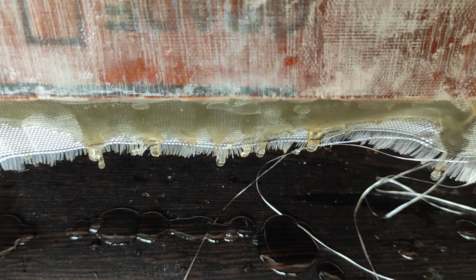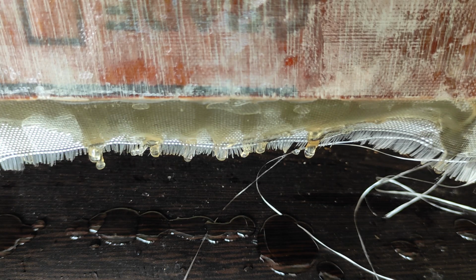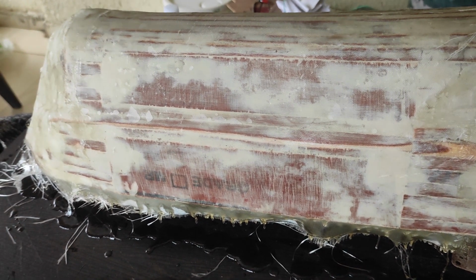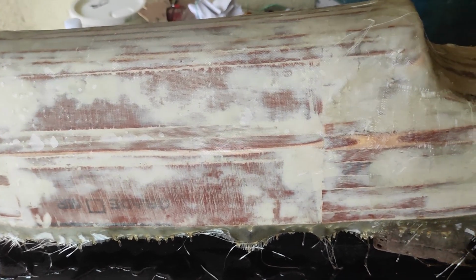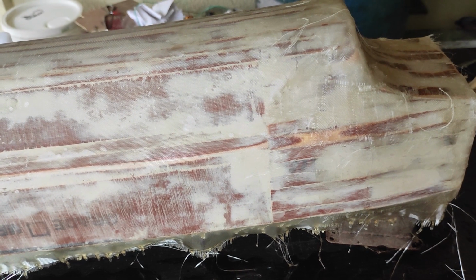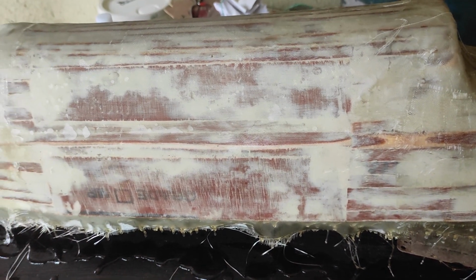For the curing process to go smoothly, you should keep it in a dry place, away from humidity, away from moisture. For me, the curing process didn't go as well because the place where I live is always moist and humid. Therefore, it took a lot of time for the resin to cure and also in the end it was tacky.